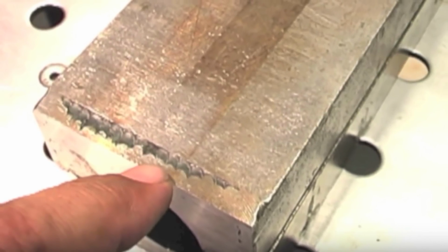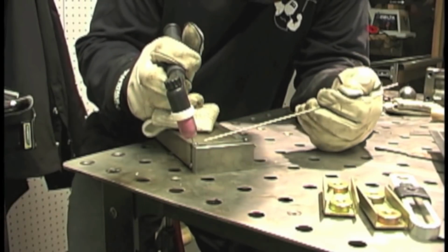It had a bunch of old MIG weld, and who knows what was in there. So the 309 just eliminated any surprises, and it doesn't bubble when you hit pockets of porosity in an old MIG weld like that. It has a tendency to not bubble and not get worse. Like regular steel, once you get porosity, it's kind of hard to cover it up, but 309 works really good for that. Not a crutch, not something you want to use indiscriminately all the time for critical welds, but it is a good choice for when you're not exactly sure the grade of the steel that you're welding, or if you're welding carbon steel to stainless steel.